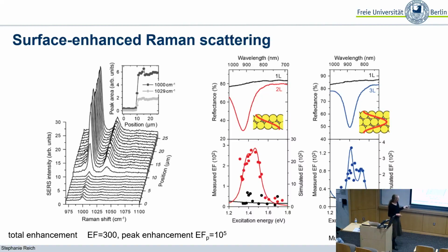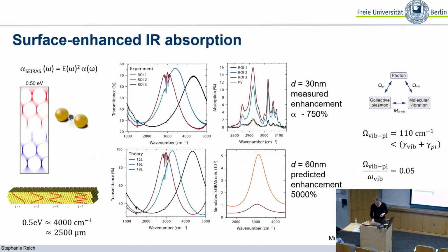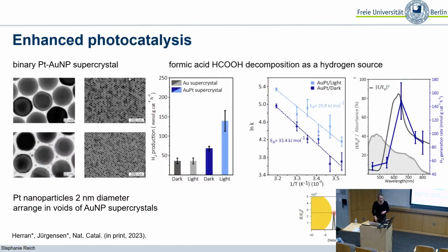So then we looked also on that we can confirm that these absorption peaks that come from the polaritons are really behind the enhancement we see in the Raman experiment by using different wavelengths and so forth. And you can do something similar in infrared absorption. But what I want to show you now at the very end of my talk is that you can also use these crystals in order to produce enhanced photocatalysis.